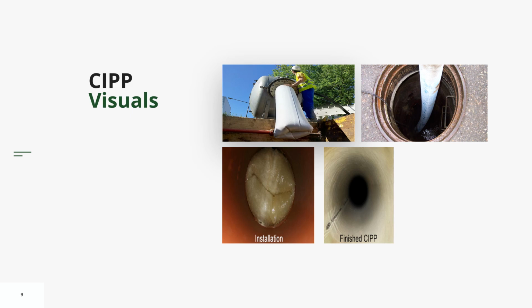You can see a little extra pool of resin on the bottom. So that resin will bond into the host pipe and cause a bond between the host pipe and the new CIPP pipe. And then as the inversion is finished, on the right-hand side where it says finished CIPP, that's a finished product. And now you see, if you notice at 7 o'clock or so, you see that band of writing. Well, that band of writing was also at the very start when we were putting resin into it. That's the plastic wrap that's around the fiberglass. And so now that plastic wrap has come on the inside, rather than the outside.